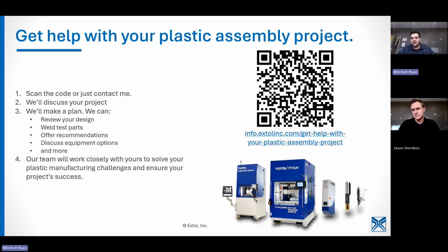Yeah. If it's higher than that, there are issues, and we should fix those because they shouldn't have to be that high. Typically, I'd say those issues are not from the welding process itself, but more that the incoming parts fall outside the typical process window. So if you've got parts that are consistent over and over again, you're going to get consistent welds over and over again.